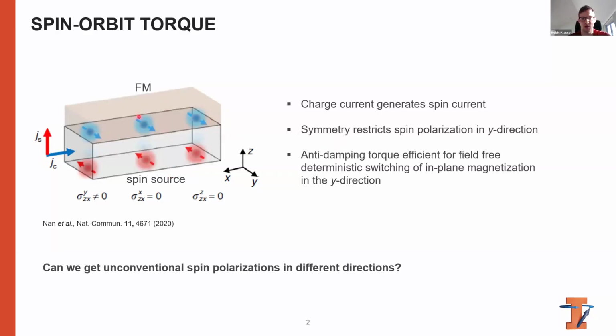If you now put a ferromagnetic layer on top of the spin source, you can get an anti-damping torque on the magnetization, which is sufficient for field-free deterministic switching of in-plane magnetization only in the y direction. So you can switch from negative y to positive y or vice versa, but you can't do deterministic switching in the z or x direction with this kind of spin polarization.